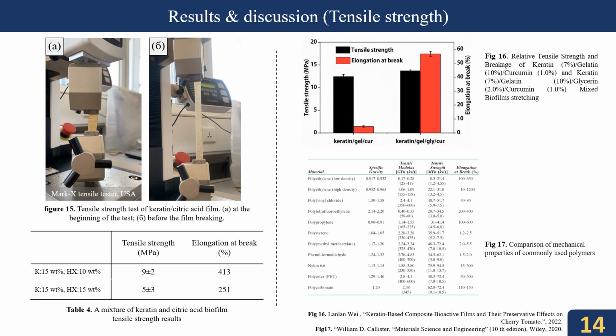As shown in table 4, the keratin and citric acid ratio of 15 and 10 biofilm shows a tensile strength of 9 megapascal and a relative elongation at break of 413%, which is a very high elongation. The biofilm with the ratio of keratin to citric acid of 15 and 15 shows a tensile strength of 5 megapascal and an elongation at break of 251%, which is also a high elongation, but showed lower mechanical properties than the ideal conditions.